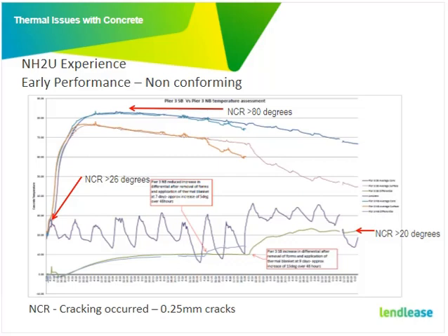If you reduce your placement temperature by one degree, the ratio to your peak temperature is typically a 1 degree reduction in the peak temperature. It's typically a 1-to-1 ratio. I also want to draw your attention to the green line on the right.